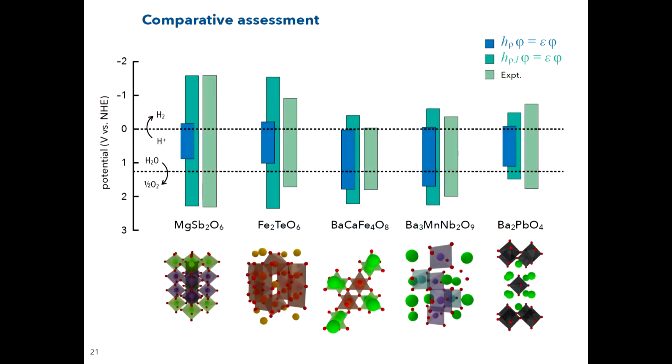So this is a GGA plus U in which you use linear response theory to calculate the parameters, and you can do that in an efficient way using new implementations that really push the limit of those techniques. But as you said, you really need to test your result against experiment and get a sense of whether or not you can trust it and what is the trend that you obtain.